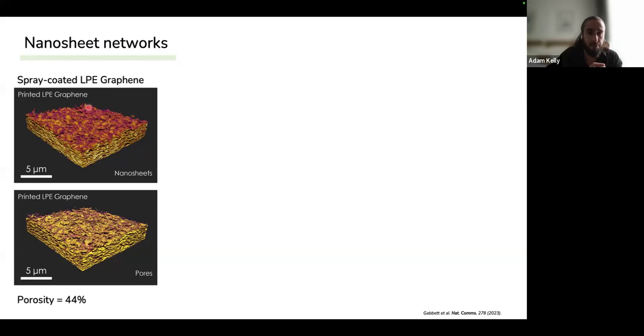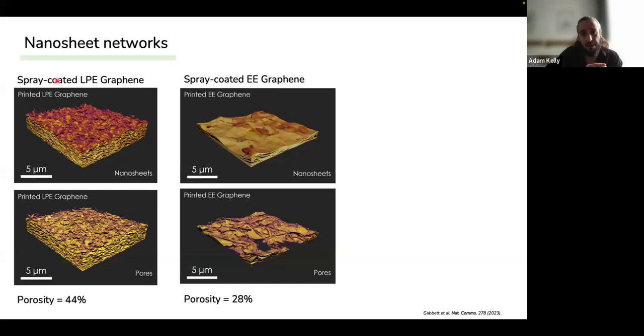So this is liquid phase exfoliated graphene, which is being spray coated. If we take electrochemically exfoliated graphene, we spray coat it using exactly the same method. What we find is that the network looks much, much better. The nanosheets conform to each other very well, and the porosity tends to be a lot lower.